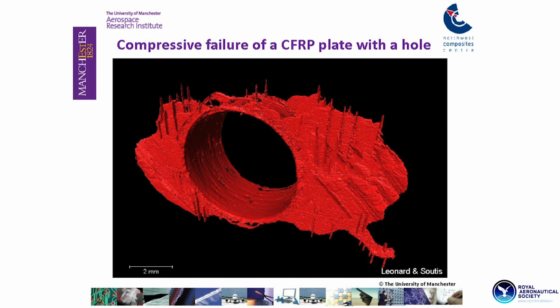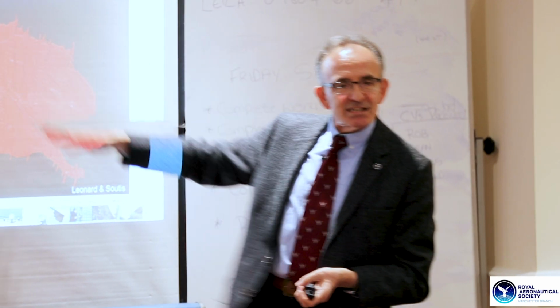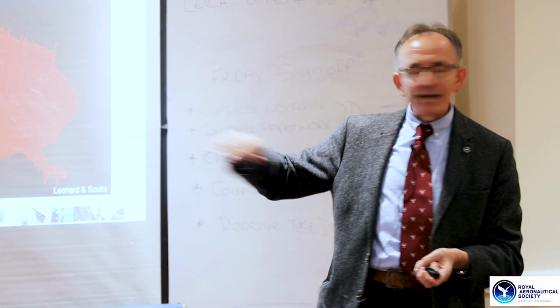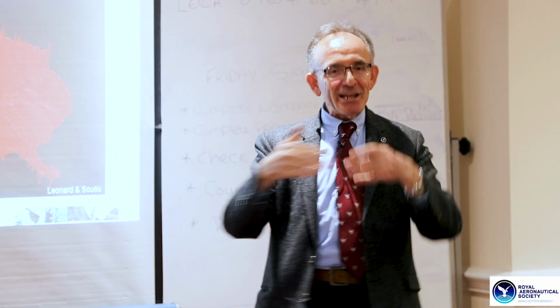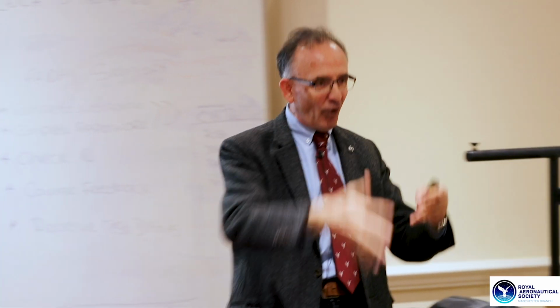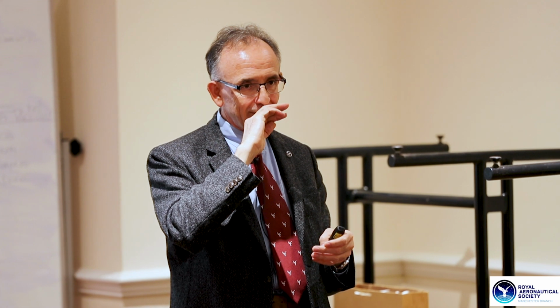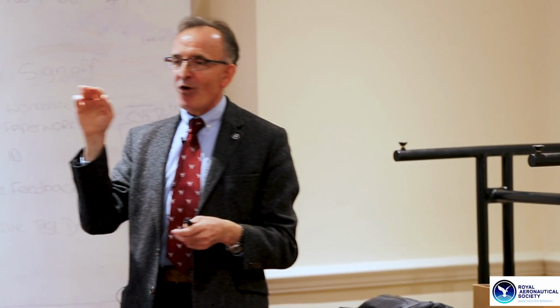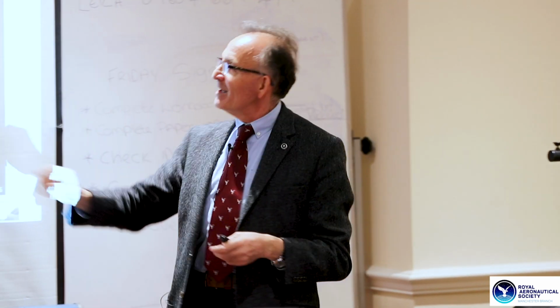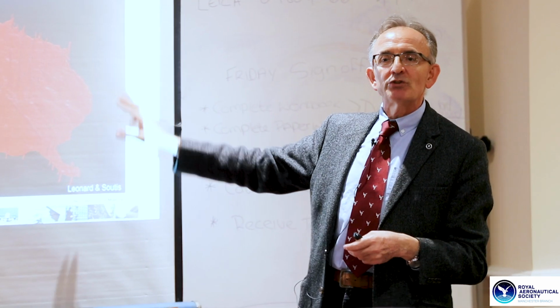Extensive amount of damage in the form of the splits that we've seen earlier, the off-axis ply cracks in the 45 plies, and those delaminations that start and follow the path of the crack. And if someone has a well-trained eye, this is an X-ray CT, X-ray computed tomography. We're going to see something is happening there.